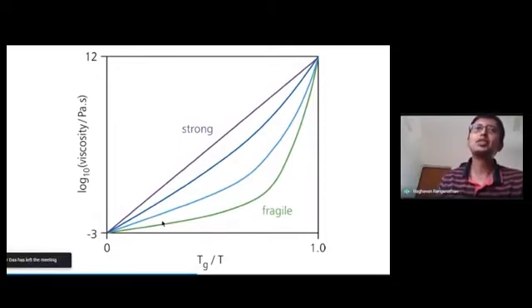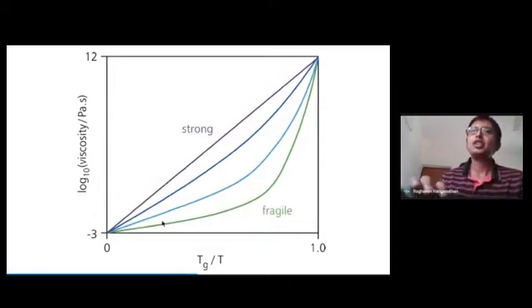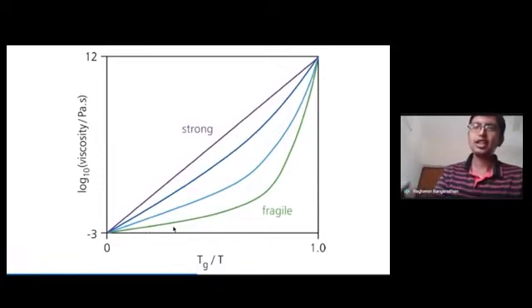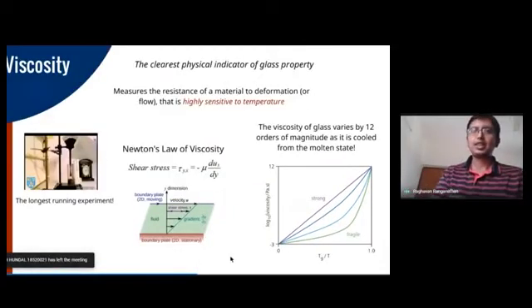So again, this goes back to what we described in terms of atomic motion in glass. When you're at a very low temperature, somewhere over here on the top right corner, the viscosity is fantastically large. It's about 10 power 12 pascal second. So essentially that means that the glass doesn't flow and it behaves like a solid. But the moment you start heating up, the viscosity starts dropping, and at sufficiently large temperatures, you will encounter glass that starts to flow. And that's what viscosity captures.